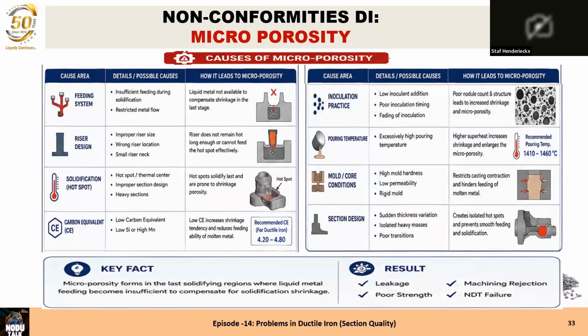Again, some overview, then we see where it is possible. The feeding system, of course, if the riser is not okay, it's already sure, and it's when there is no liquid metal anymore at the moment of solidifying shrinking. In that area you can have it. It's sometimes under a riser because the riser neck solidified and the last solidification shrinkage under the riser is not compensated anymore, and then it's under the riser. And that you see in the riser design. If the riser is not feeding until the last moment, it will not be able to compensate this micro porosity.